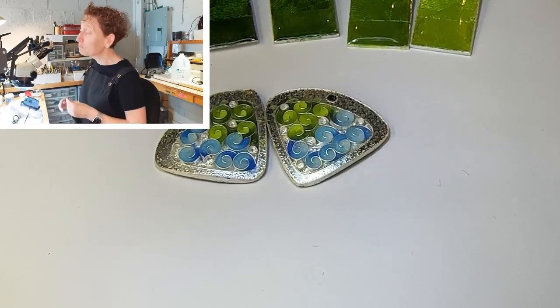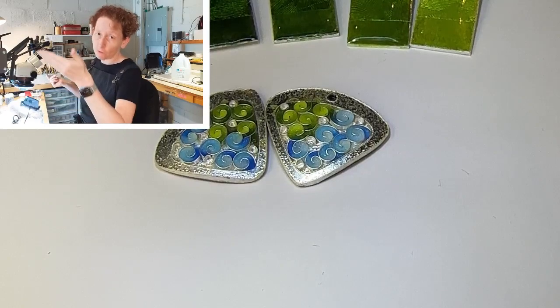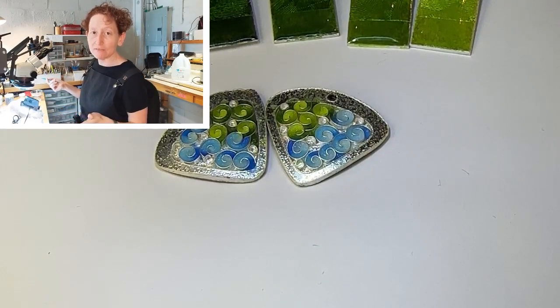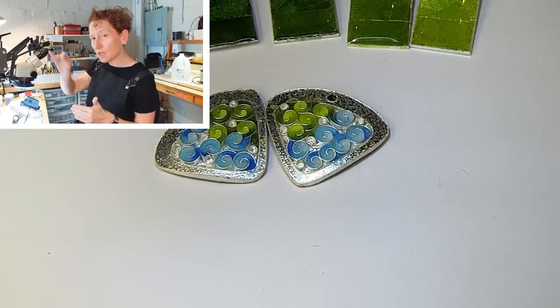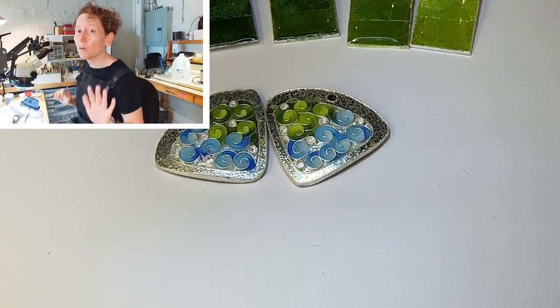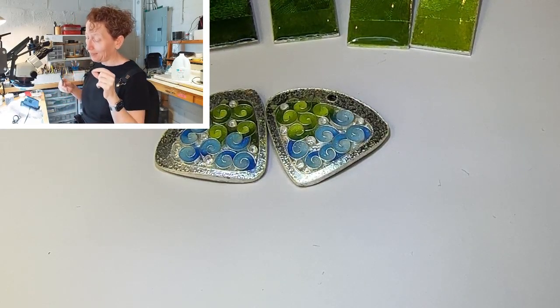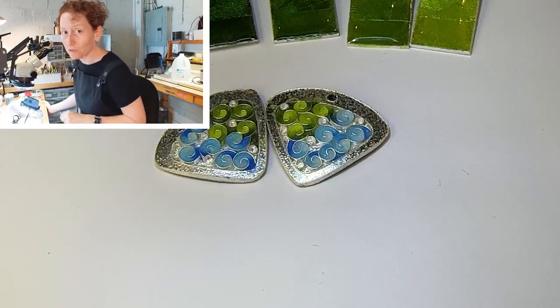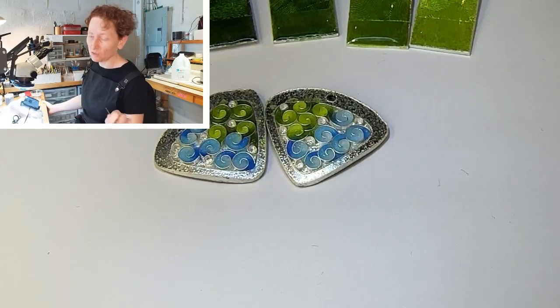Especially since my kiln has a setting. It's set for 1430 degrees Fahrenheit, 776 Celsius, and it's going to crest up to about 1450 and go up and down, but it's not going to go above that. So I don't have to worry about the silver melting. It could be in there for an hour. To be honest, I've left something in the kiln for like 45 minutes one time, and it was just fine. It was blues and greens.